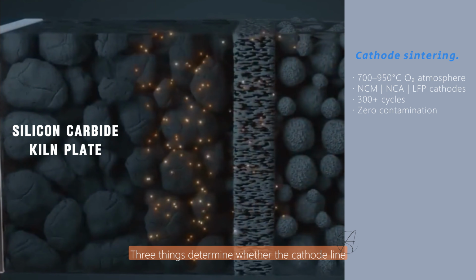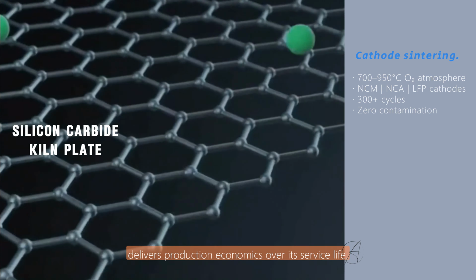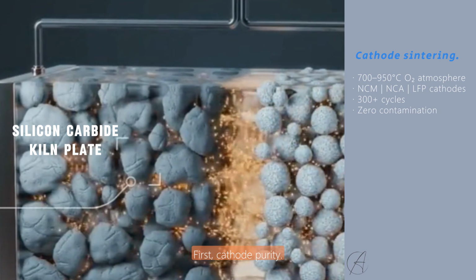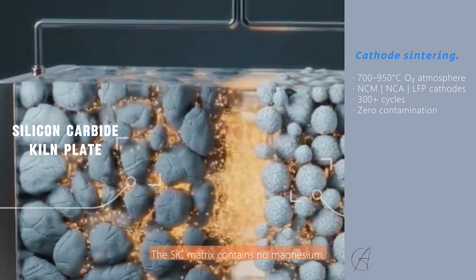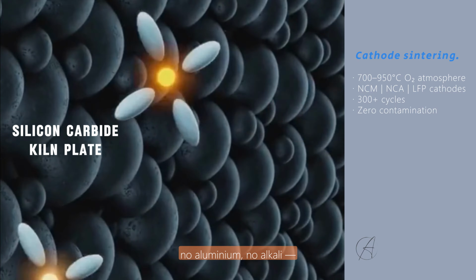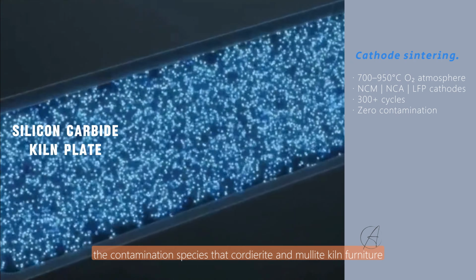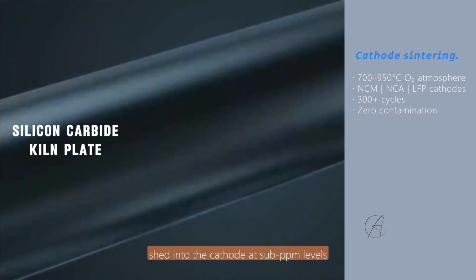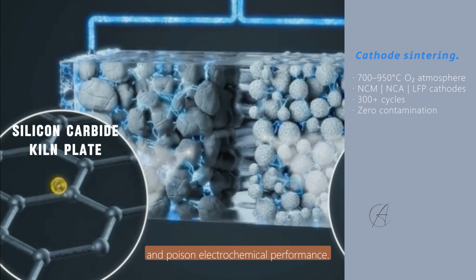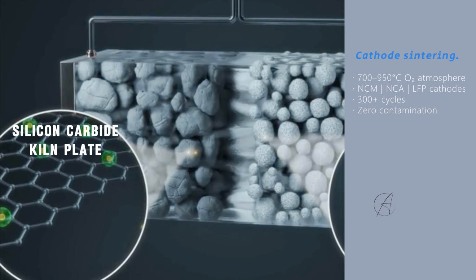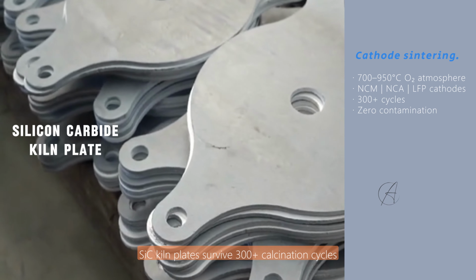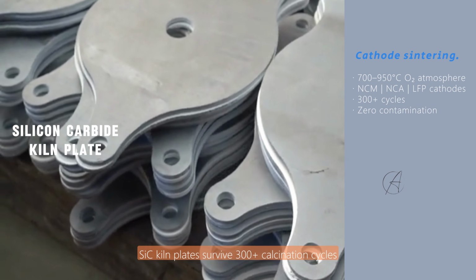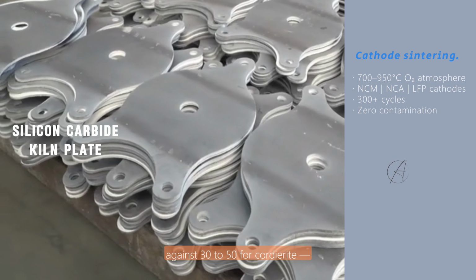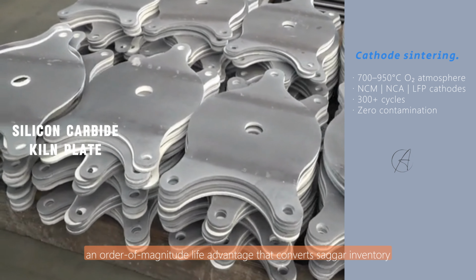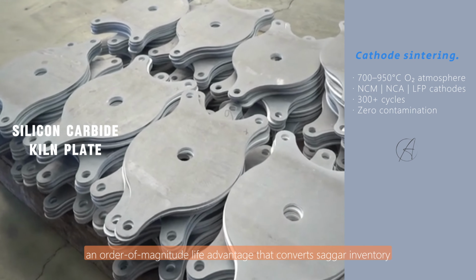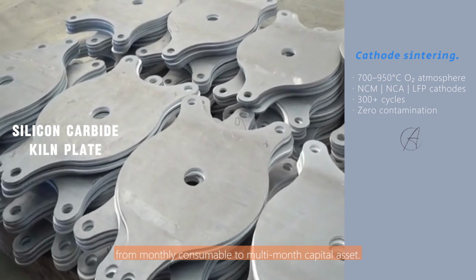3 things determine whether the cathode line delivers production economics over its service life. First, cathode purity. The silicon carbide matrix contains no magnesium, no aluminum, no alkali. The contamination species that cordierite and mullite kiln furniture shed into the cathode at sub-ppm levels and poison electrochemical performance. Second, cycle durability. Silicon carbide kiln plates survive above 300 calcination cycles against 30 to 50 for cordierite, an order of magnitude life advantage that converts saggar inventory from monthly consumable to multi-month capital asset.